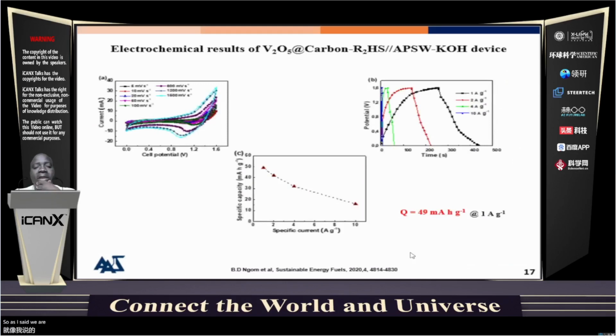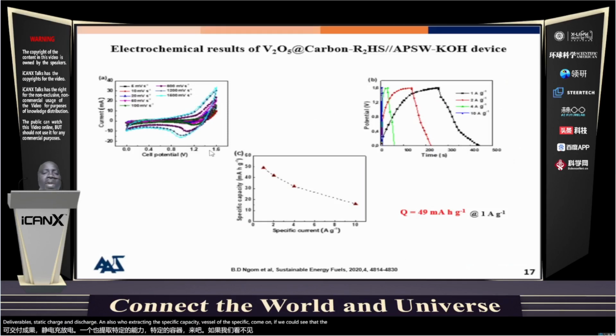So as I said, we are interested in the electrochemical property of the material. Then we took this material and produced a device, which we first look at as a positive electrode, to see how the material responds, looking at the CV, galvanostatic charge and discharge, and extracting the specific capacity versus the specific current. We could see that the charge mechanism is a Faradaic capacitor behavior, as it is an oxide, and the electrolyte that we are using is 6 molar KOH. The nonlinearity of the charge and discharge confirms the mechanism, which is confirming the CV measurement that we have here.